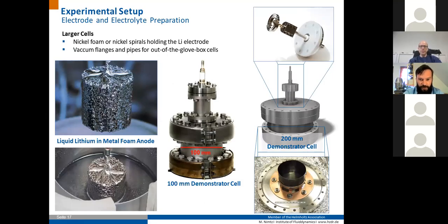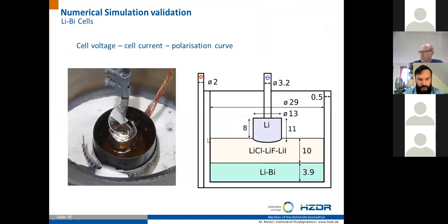Here you can see such a closed cell, 100 millimeter diameter, made from vacuum components, and here a sketch of a larger demonstrator cell, 200 millimeters, which then will be built in a similar way to the smaller cells. Here we also use nickel foam as displayed left, or a nickel spiral as an electrode holder for the lithium. And as I said, this will be done with vacuum components.